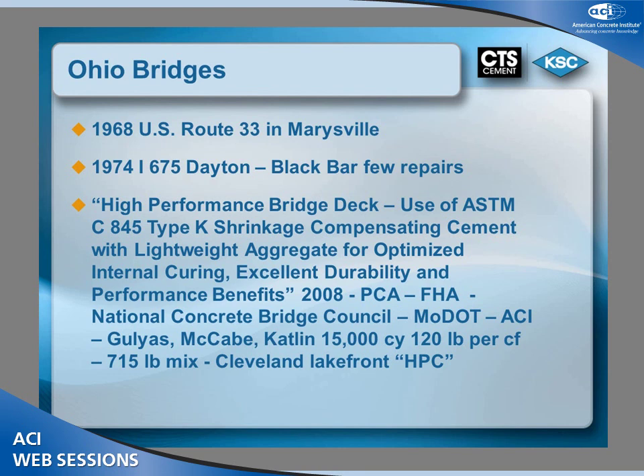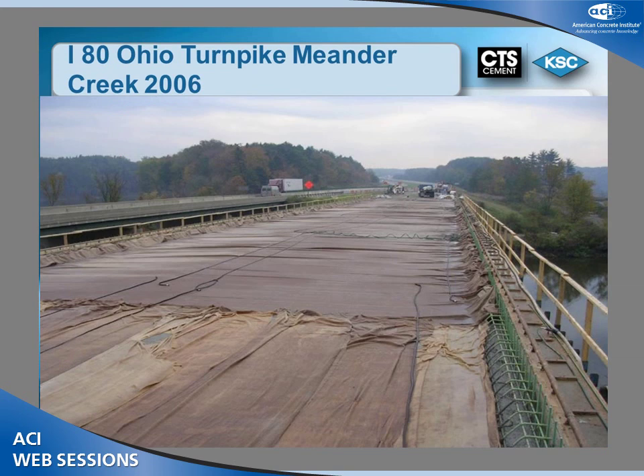There was 15,000 yards of concrete at 120 pounds per cubic foot unit weight, okay? It was a 715-pound cement mix design, of which 100 pounds was the component. This is on the lakefront, and they call this HPC. I believe the reason why I wanted to show this HPC is because we've overused this terminology, but it is a high-performance concrete, okay? It does provide for performance that you do not get with Portland cement concrete.